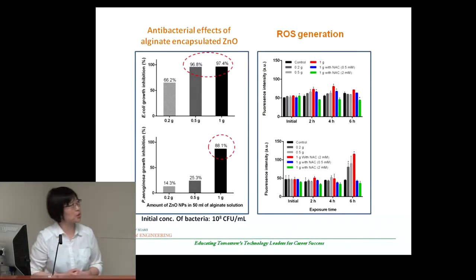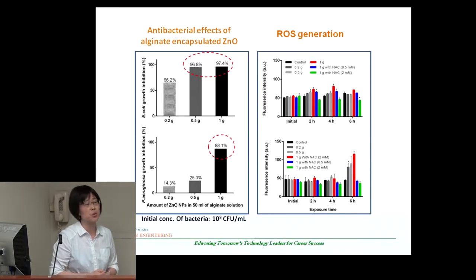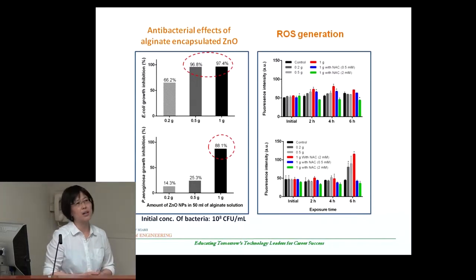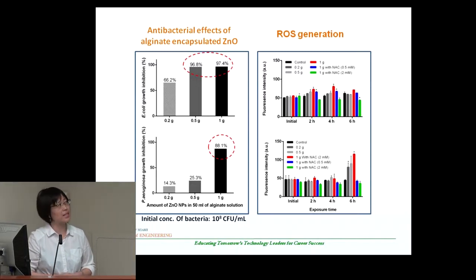So in order to confirm the possible mechanism, one of the hypotheses we came up with is the release of reactive species. So what if we minimize the ROS generation? So we added the scavenger NAC. NAC is a scavenger of ROS. So adding the NAC, we found significant inhibition of ROS generation, which confirms one of the primary mechanisms responsible for treating the bacteria in water.